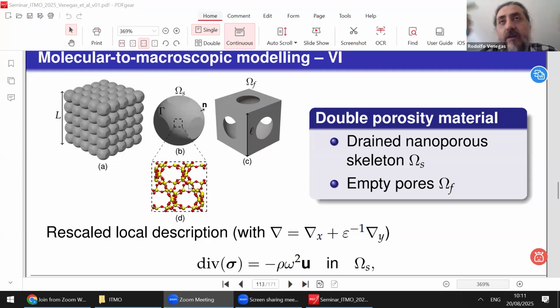The only difference is that when the material is random, you don't really have an easy way to identify a representative elementary volume. So you have to say, okay, this representative elementary volume is this, and then you make simulations, and then you create another one, and then you start combining them using, let's say, an ensemble average to work out the effective properties. With a periodic material, you just have this REV that is well defined. You solve it in there, and you get your effective properties. So that's the main difference. In one case, you've got a very well established geometry where you solve the problem, and in the other one, you have to do many realizations and then work out its effective properties.